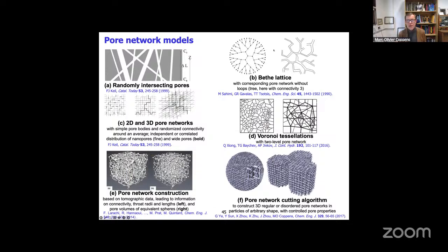If you have Bethe lattices, so no network effects, no loops, but just a tree-like network, like in this Bethe lattice, again, you can analytically solve your equations. That's shown in this paper by Sahimi, Gavalas, and Tsotsis, which is a very beautiful review paper I will mention and relate to at the end. Voronoi tessellations, but now more recently, there are also pore network reconstructions based on X-ray microtomography and even nanotomography of porous materials that can help you reconstruct the pore space so that you have truly an input to what are otherwise rather artificial pore network models like the ones under C here.